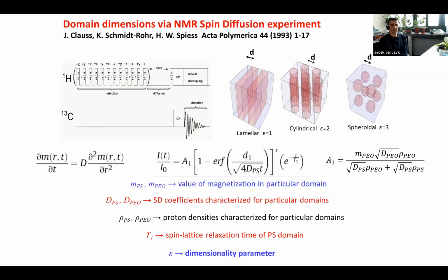That's one thing, and above that, moreover, we can also estimate the so-called interfacial thickness, and this parameter is of great importance in microelectronics, because it really determines the sharpness of our structural motifs. So it really determines the eventual feature size produced via block copolymer lithography.